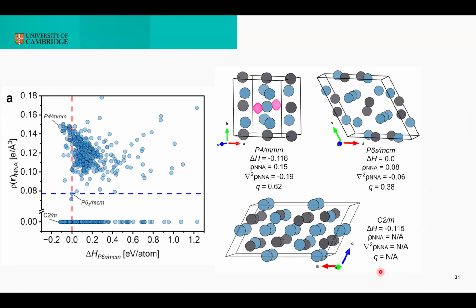In our research, on one hand, this phase was found at 20 GPa, which is the one that here I report as the P63/mcm. Here you have the relative entropy compared to this phase that is the 0, and also the amount of electron density at the maximum, so at the non-nuclear attractor. But on the other hand, it was found out that this was neither the most stable nor the most electride phase at 20 GPa.